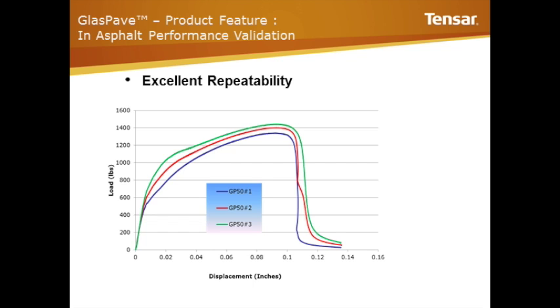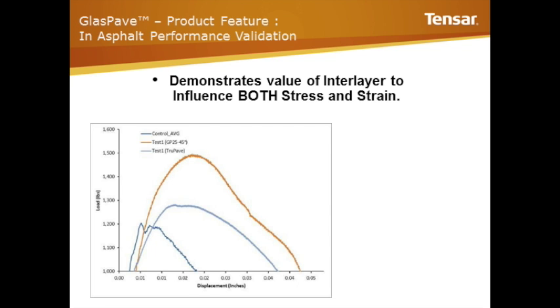Here's an example of the repeatability. So these are three samples. You always do 3 replicates. It's a relatively inexpensive test, and here you can see outstanding repeatability. Those of you that have studied or looked at interlayer testing in the past will see that this blows research away. I can refer you to the Nottingham study done in 2000 in the UK; if you go and see, their results were pretty much all over the place, and they did beam testing. So this has given us a great sense of confidence going forward.